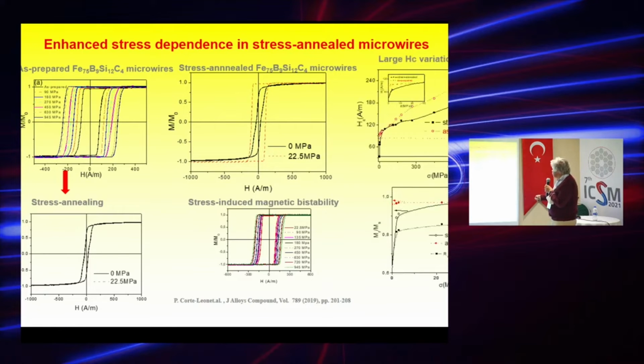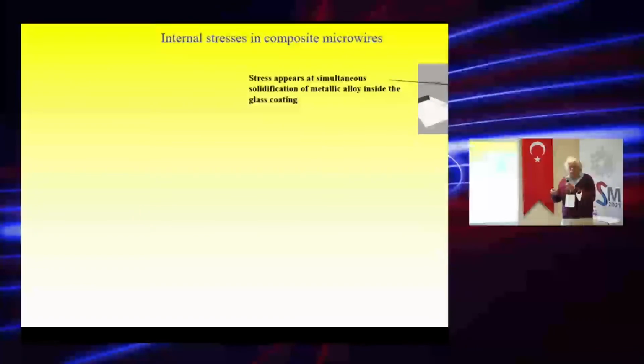So if you plot the dependence of coercivity on applied stress, this is for as-prepared materials and for the stress-annealed ones. You can see the variation is much stronger in the case of stress-annealed samples. So for application in magnetoelastic sensors, it's quite relevant as well to have this stress annealing-induced magnetic anisotropy.